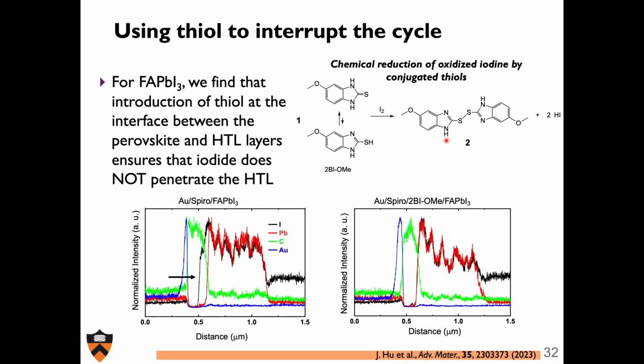And one thing that I want to show you, just because it's nicely drawn out from what I showed you a few slides back, if I take a system like Spiro with an iodide perovskite, I'm showing here again that iodine can leach into the Spiro layer. You see this black trace is the iodine that has really infiltrated the Spiro. And if I put this thiol between Spiro and the perovskite, you can see that the iodine and lead traces follow each other very well. And that's because it's actually holding back the iodide from being infiltrated, because it's never actually getting oxidized without being just reformed into iodide through the action of this thiol compound.